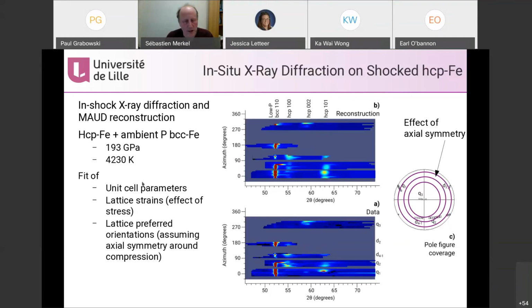The data looks very noisy, and the coverage is not complete, far from it. But we're lucky that we can assume that there is some form of axial symmetry around the shock direction, which allows us to make a lot of assumptions on how the stress and the texture should look like. And then HCP materials have a lot of redundancy, so you don't need so many peaks to get some data. And then you can get a fit of unit cell parameters and lattice strains, which is the effect of stress, the way peaks move with orientation. The variation of peak intensities with orientation is texture.